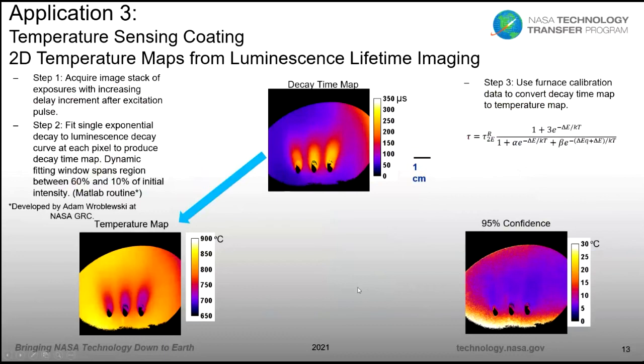Now, first, I wanted to show you how you can construct a temperature map. It takes several steps of acquisition and image processing. The first step is an acquisition stage where you acquire an image stack of exposures, where each exposure has an incremental increase in the delay after the laser pulse. That laser pulse, remember, corresponded to the broad green light you saw on the last slide that spread over the area we want to map. It's only on for about 10 nanoseconds at a time, and then we see how the luminescence emission decays as soon as it goes off.